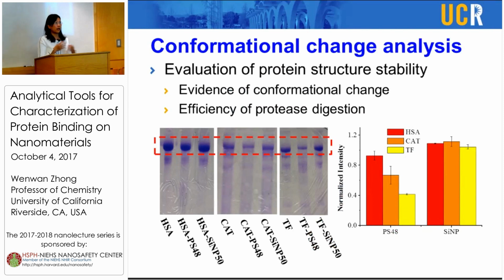Here we remove the effect of the particle on trypsin by pre-incubating the proteins with the particle. We also incubate the proteins with the particle at a high protein coverage, to prevent impact from the particle itself on trypsin. But if the trypsin activity were affected by the particle itself, then the HSA effect should not be the same, right? So that's what we believe is actually due to binding induced conformational change.